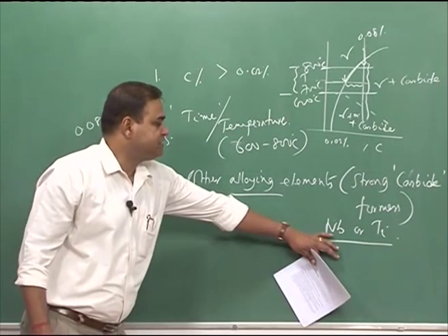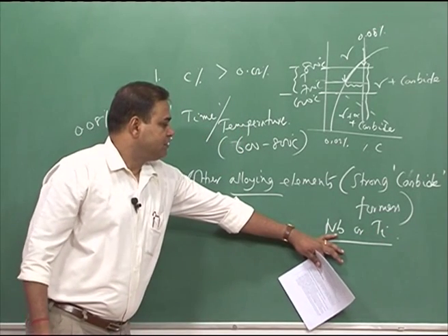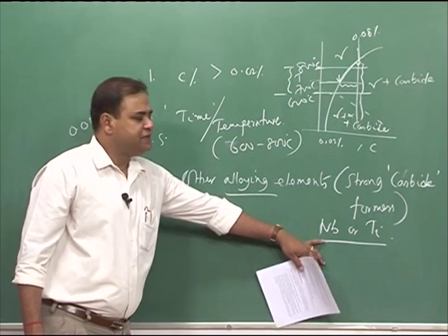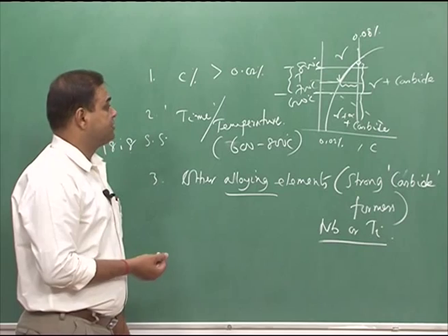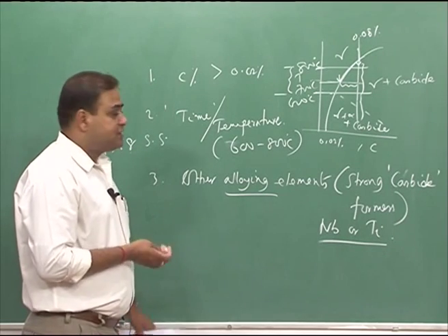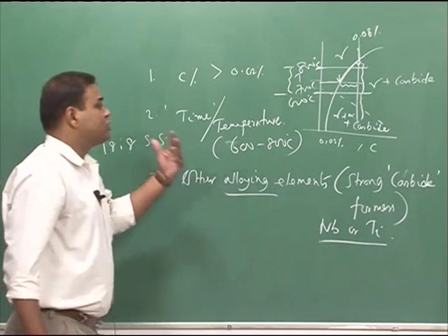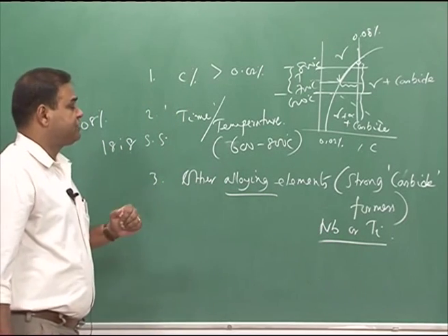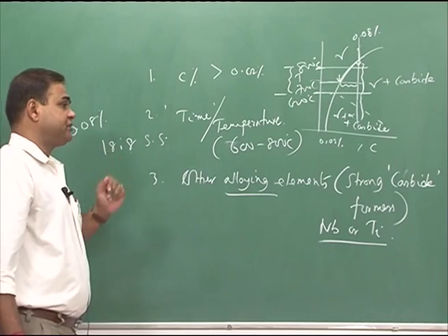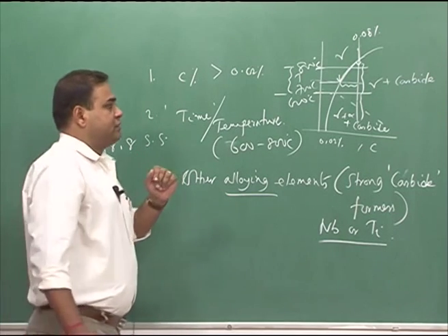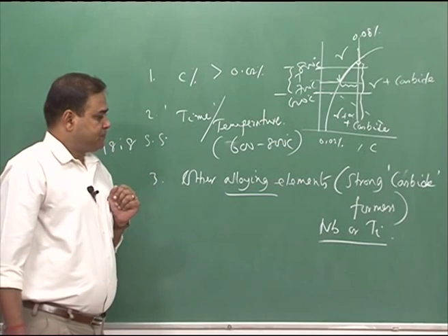If we have these highly carbide forming elements and their affinity towards carbon is more than chromium, then this affects the possibility of chromium carbide precipitation, since chromium is important in giving the stainless property.